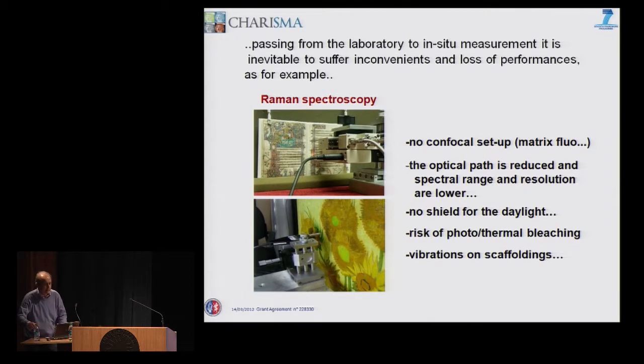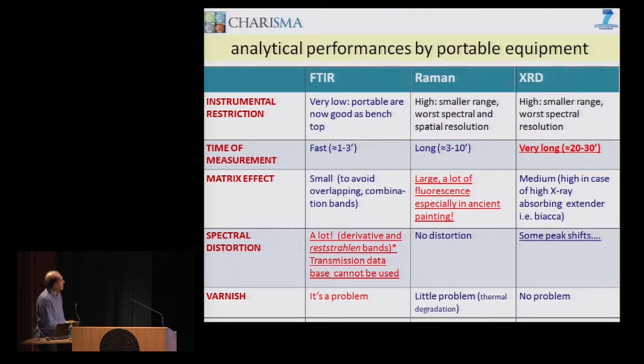I'm sure that you all have very clear ideas that passing from benchtop instrumentation to work in situ with portable equipment implies loss of performance and inconveniences. For example, talking about Raman spectroscopy, you have no confocal setup, and this implies a lot of fluorescence from the matrix. The optical path of the small instrument is reduced, which implies a smaller spectral range, and the resolution is also lower. Usually there are no shields for the daylight, so you have to carry out Raman measurements in dark rooms. You have to pay attention to the risk of photothermal bleaching, because you are working on artworks that are very precious, like in this case. And if you are working on scaffoldings, as I have shown before, you have to pay attention to the vibration of the system. These inconveniences are shown by Raman, but inconveniences are also shown by other techniques.